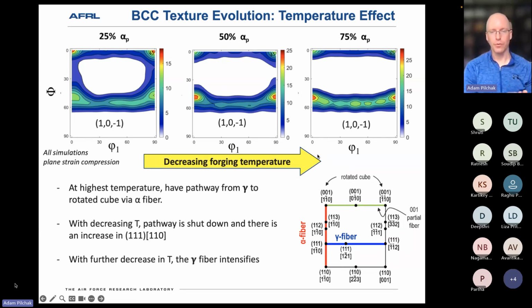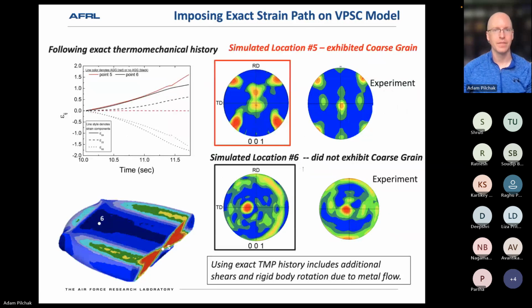However, nobody really likes lower forging temperatures because you need more reheats. It's more stressful on the die, and you need to replace those earlier. And so that's not necessarily the most preferred route to avoiding this effect, but it is an option.